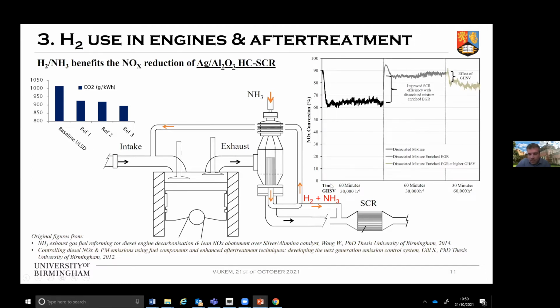And then what we obtained was that from a very low initial conversion efficiency, again at a temperature range around 200, 220 degrees, the conversion efficiency without the hydrogen and ammonia mixture was around 15–20%. Then by injecting hydrogen and ammonia, we were able to increase the effectiveness up to 60–65%. And by playing a little bit with the engine, using external recirculation, we were able to increase the NO2 to NOx ratio pre SCR, and then to increase the conversion efficiency of our SCR close to 90%.